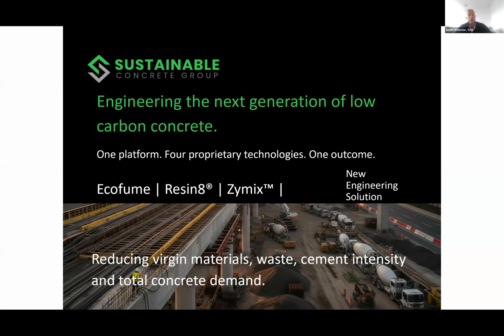We basically have 3 or 4 different products that are currently being used, and again, all directed around reducing the carbon footprint of concrete. They've developed a product called Ecofume, which is at this stage just going through certification as a silica fume replacement. It currently has some test data that's come back with a chloride content of 0.004, so extremely low, and is just going through the processes for the AS certification at the moment.